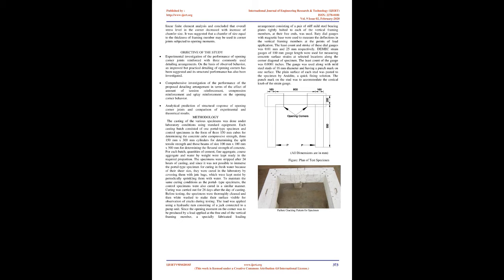Dar and Singh, 2004, investigated the effect of chamfer as well as reinforcement detailing on strength and behavior of opening corners. 4 specimens with detailing system comprising of loop steel and inclined bars with different amounts of chamfer size provided at the inner corner were investigated. In the first specimen no chamfer was provided and chamfer sizes of 60 mm, 120 mm, and 180 mm were adopted for other specimens. It was observed that cracking in the corner region reduced with increase in chamfer. Failure load and joint efficiency increased with increase in chamfer. Inclined bar at the reentrant corner gets more lever arm and loop steel gets additional anchorage due to presence of chamfer.